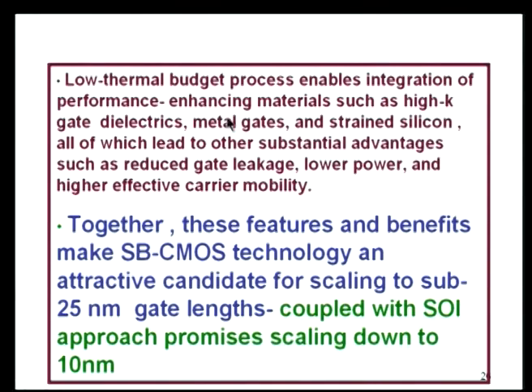Also, low thermal budget to make the metal contact onto the source drain. You do not have to have high temperature diffusion, and if it is low temperature Schottky, it is excellent to make high K dielectrics. That is why people are looking into metal semiconductor source drain. When you put high K dielectric, you may realize the gate etcetera, we can even go for metal gate. Then afterwards, source drain, you do not want to do diffusion, you want to do it at low temperature. We can use that metal semiconductor contact. So, that is why people are looking more and more into that in nanoscale devices. Together, these features and benefits make Schottky barrier CMOS technology an attractive candidate for scaling to sub nanometer, below 25 nanometer, coupled with SOI approach promises down to 10 nanometer.